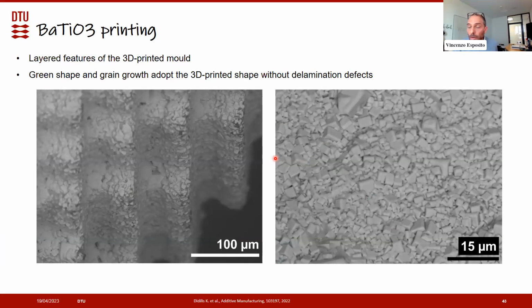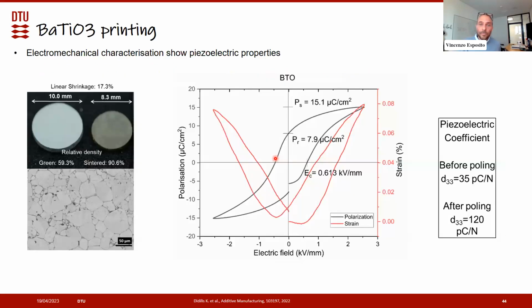material. The finish of the pieces is decent and can of course be improved. We have some examples, but in the end what we get is always a nice and dense piece. We started with commercial feedstock, then developed feedstock by ourselves and printed several shapes. And the shape, what to print, is actually one of the questions that arise when you start doing additive manufacturing. The first thing we did was cylindrical pellets, actually to test the properties of our material.